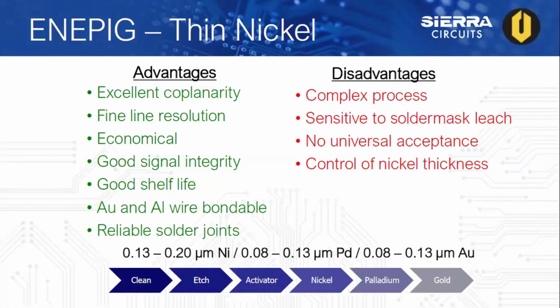Since there is no IPC specification for thin nickel final finish, some thicknesses that have been tested fall in the ranges shown here: 0.13 to 0.2 microns of nickel, 0.08 to 0.13 microns of palladium, and gold as well for thickness.